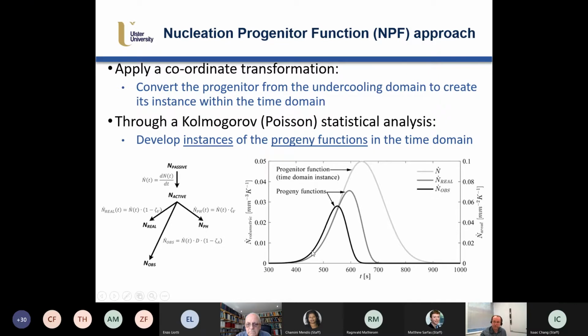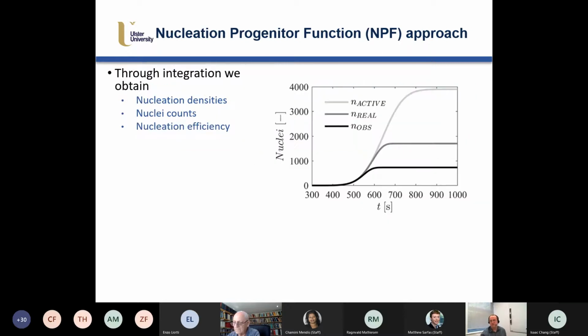You also have a progeny for the 2D observation on the 2D plane, and because it's separate units, we have it here on the right hand side, so it looks slightly different, but this is also derived from the progenitor. There's one progenitor that applies across the entire domain as a description of the grain refiner. But every single nodal point in this simulation and in the domain will have its own progeny that develops over time. So there's a lot of information available from all of these progeny that all come from one progenitor.